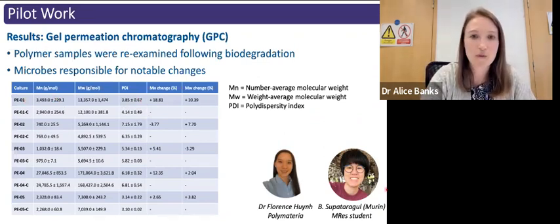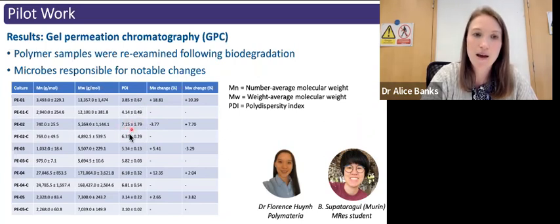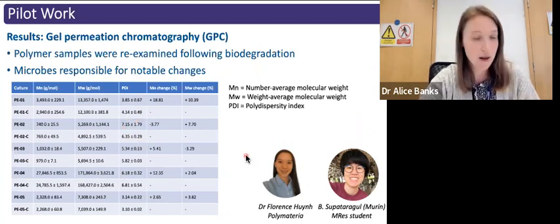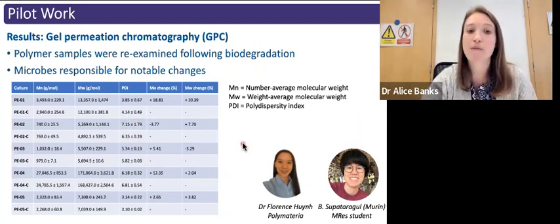And another example would be polyethylene 2, and we can see that the inverse is true here. So in the experimental sample, we've got a higher PDI than in the control tube. And this might be the result of microbial activity cleaving many of the chains, leading to a whole range of different polymer sizes. Another reason could be that some of the particles may actually be larger as a result of biofilms forming on these.